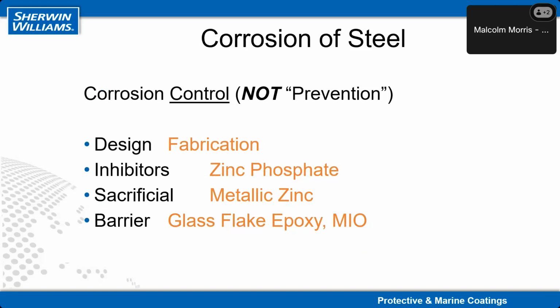First of all, we can design our structures to be less prone to corrosion. If structures have things like water traps and back-to-back steel eliminated from the design, that will greatly assist the longevity of the particular design. We can put chemical inhibitors into paints. The most common one you'll see out there is what we call zinc phosphate, which chemically inhibits the corrosion chemical reaction. That's the most common one these days.